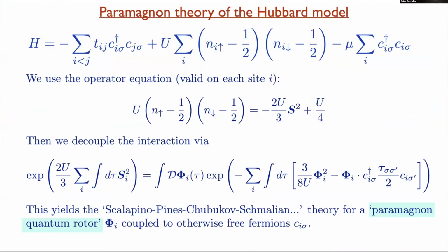Okay, so we start with the Hubbard model, the one-band Hubbard model, and we rewrite the Hubbard interaction as something like spin squared times a constant. And then you do the Hubbard-Stratonovich transformation, and you get this field phi, which couples to the spin density of the electrons. So this is a very well-trodden path, going back to theories of helium-3 and ferromagnetism, and various people, Scalapino, Pines, Chubukov, Schmalian, many people have used this kind of theory of a fluctuating paramagnon coupled to a Fermi surface as a theory of spin fluctuations in the cuprates. All right, so that's all fine. I'm happy to use it, but if you use it to all orders, when you don't break symmetry, you always get a large Fermi surface.